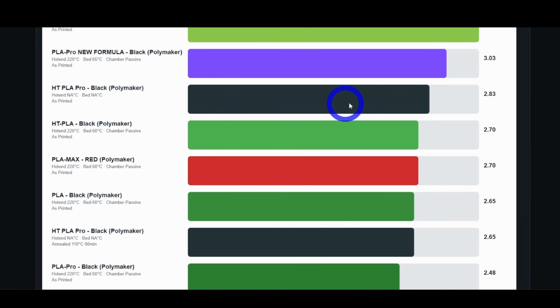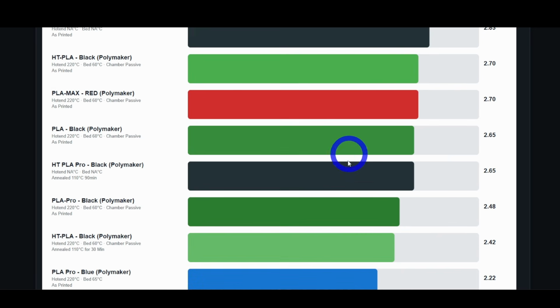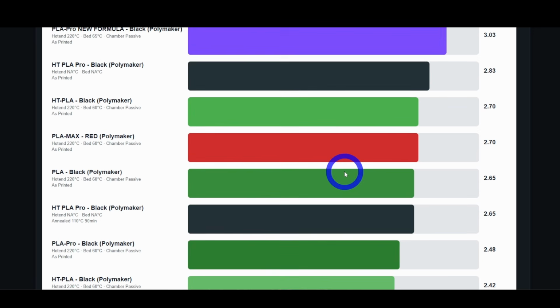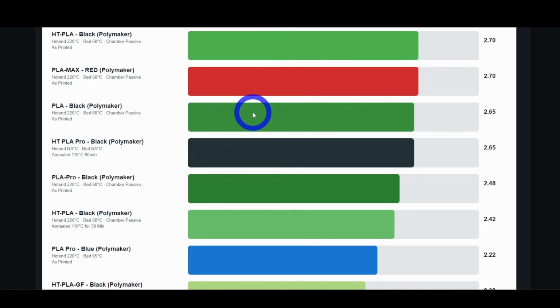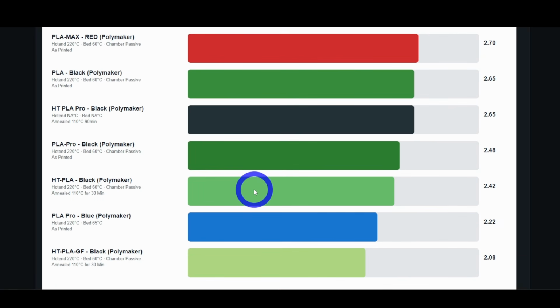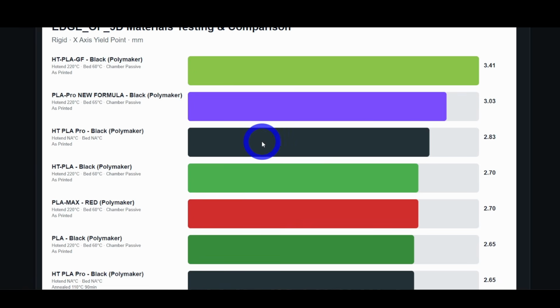The yield point: the machine starts at 0 millimeters, starts pulling, and measures where it peaks out. As printed, the HT-PLA Pro peaked at 2.83 millimeters, and the annealed HT-PLA Pro at 2.65 millimeters. Here's the other HT, the original version: 2.7 on the raw and 2.42 on the annealed. So pretty similar results there.